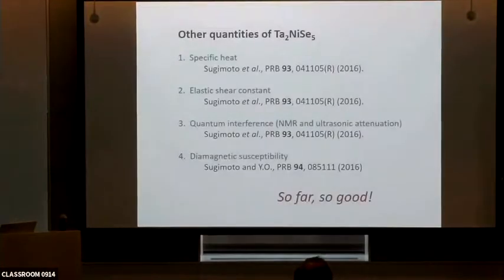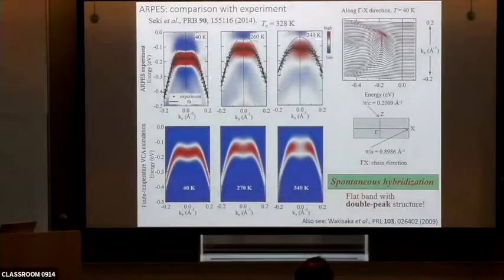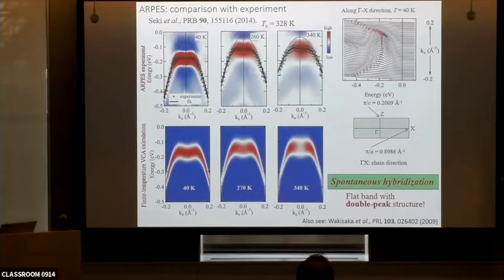What about this one? This is a standard photoemission, ARPES photoemission. Right, so we had that discussion, that I think Dr. Kang from Rutgers argued, and the optics people argued that their data were somewhat inconsistent with that photoemission. Because I would agree with you that the photoemission data at 340 Kelvin by itself is suggestive of a transition which is destroyed by phase fluctuations with the amplitude remaining, which is kind of what you mean by BCS. And we heard some people say that optics and the tunneling were not so consistent with these data.